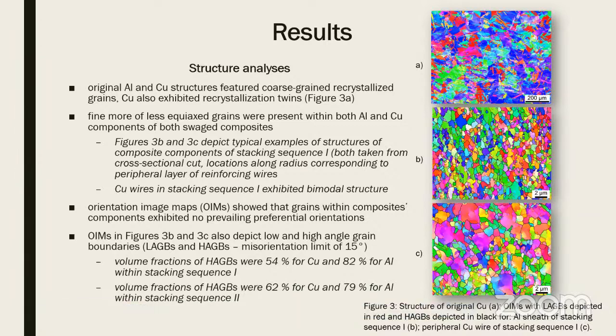After swaging, we acquired more or less equiaxed grains, especially in the aluminum components of both the composites. An example of such a structure is seen in figure 3b, which depicts the aluminum sheath of stacking sequence 1. In the copper components, there was a bimodal structure, an example of which is seen in figure 3c.